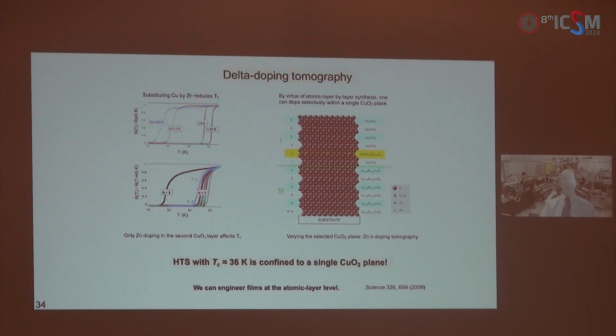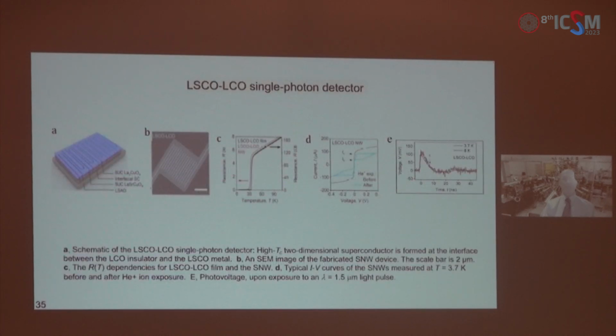What we found is that both in resistivity and in mutual inductance, Tc stays basically undiminished, meaning the resistivity and superfluid density, except in one sample, and that's the one in which zinc was doped in the second lanthanum cuprate layer after the interface. In this way, we were able to prove that interface superconductivity is confined to a single copper oxygen layer, which makes it the thinnest superconductor known. And yet the Tc is about the same as in the optimally doped lanthanum strontium cuprate.